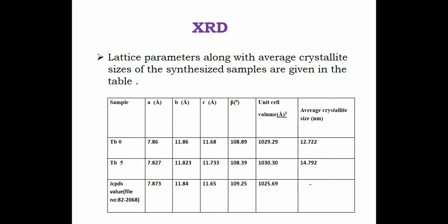The average crystallite size was calculated by the well-known Debye-Scherrer equation. For TB0, it is 12.722, and for TB5, it is 14.792. The average crystallite size of the terbium doped sample was found to be increased. The lattice parameters of the samples were calculated using the d-spacing equation. The lattice parameters and the average crystallite size of the samples are presented in the table. Standard values as per the JCPDS file are also given for comparison. A slight change in the lattice parameter values is noted due to the incorporation of terbium ions.